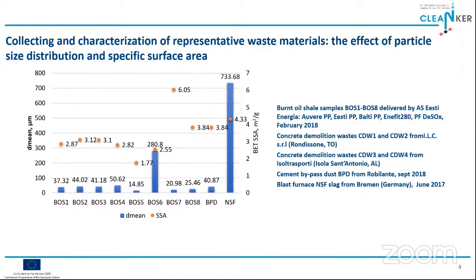According to previous studies done by our lab as well, the pulverized firing ashes from power plants are characterized by lower specific surface area, and the circulating fluidized bed ashes by higher specific surface area. Here, most of the burnt oil shale ash samples vary between 2.55 square meters per gram and 6.05 square meters per gram. The mean particle size of the total ashes is similar to the electrostatic precipitator ash of the same boilers, with the exception of the BOS 6 sample, which has an exceptionally high particle size, as indicated here.